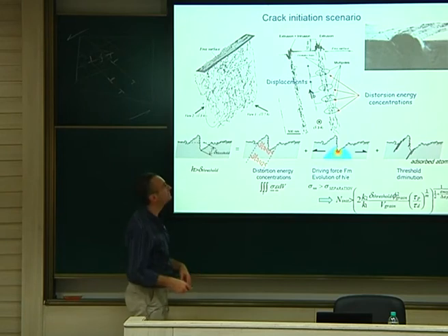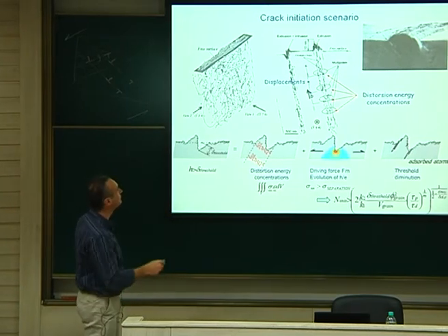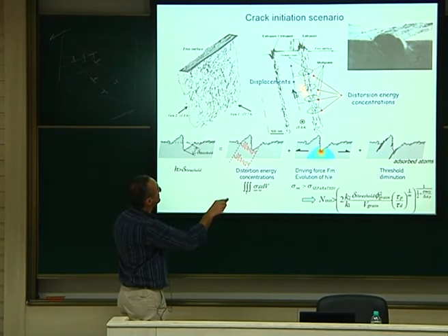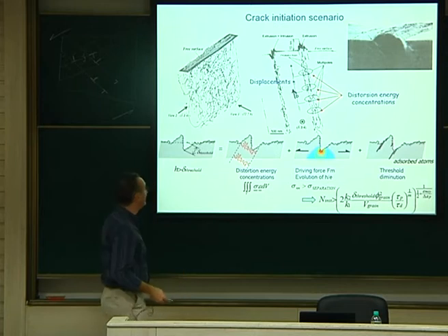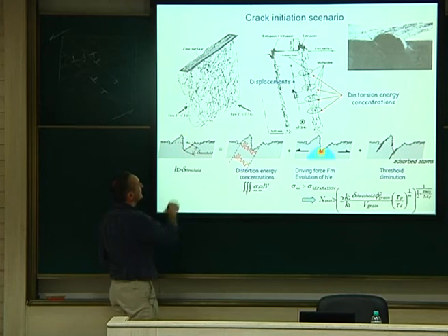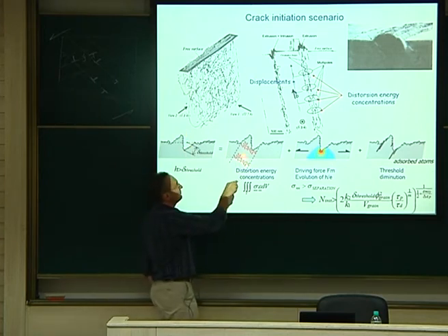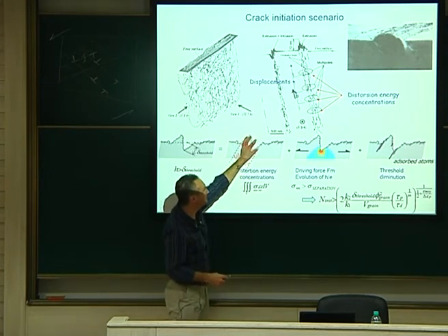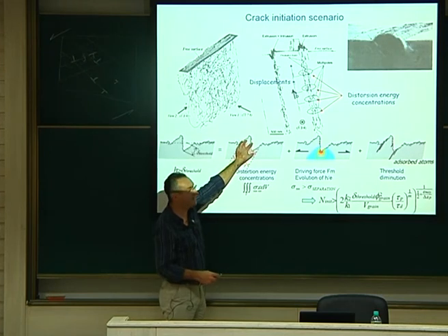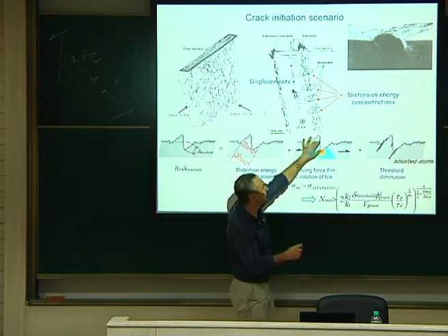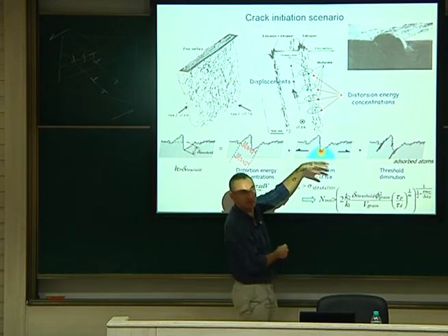It's not a plot we did by imagination. This is DD modeling. You have the extrusion, intrusion shape like that. You have your multipoles, which are moving like that. You have your highly mobile dislocation at the interface. So what happens is after a given threshold, after a given shape of your extrusion, when a set of prismatic loops will reach the surface, many prismatic loops here, when they come to the surface, they will give the energy here, locally, enough to open the crack, plus the shape factor will give you the stress component to open the crack. This will open the crack, okay, and then it will damage your material.